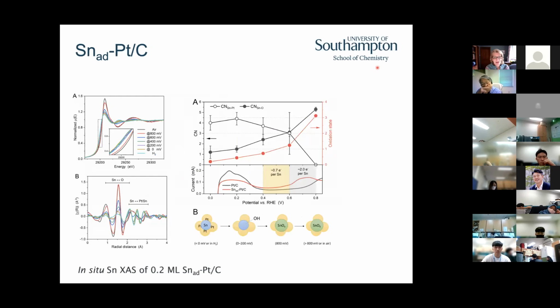Of course, we did the X-ray absorption spectroscopy, and we did it as a function of the potential, so in an in-situ environment. From the tin perspective, the edge shifts more negative as we reduce the potential, so we're reducing the sample, or shifts more positive to higher energies as we oxidize the sample. Here, instead of showing you the amplitude of the Fourier transform, we're showing you the phase, because it really points out the differences in the tin-platinum coordination as we go from the most positive potentials, where it's really the tin oxide. See that that's all decaying, and we increase the number of metal neighbors as we reduce the sample.